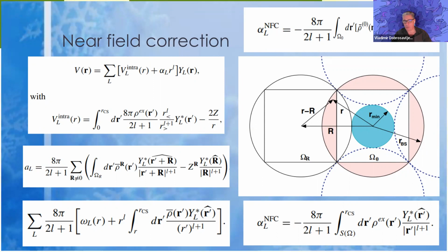You can think of a point charge, but then the charge that's transferred to chlorine, half of it goes into the interstitial site, and it's not just sitting on the chlorine, or in magnesium oxide. The charge on the oxide is not actually on the oxygen; it's actually everywhere.